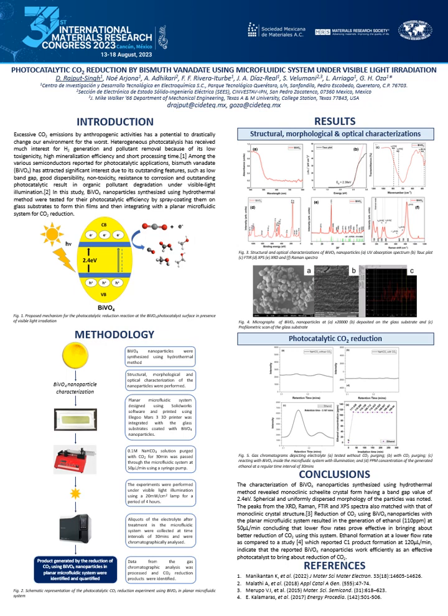for carbon dioxide reduction. Now this diagram here is a proposed mechanism for the photocatalytic carbon dioxide reduction occurring at the surface of bismuth vanadate nanoparticles. Here, under visible light illumination, an electron from the valence band of bismuth vanadate tends to jump towards the conduction band at an energy of 2.4 electron volts. This electron then interacts with the carbon dioxide molecule, which is anchored to the bismuth oxygen bond, and then brings